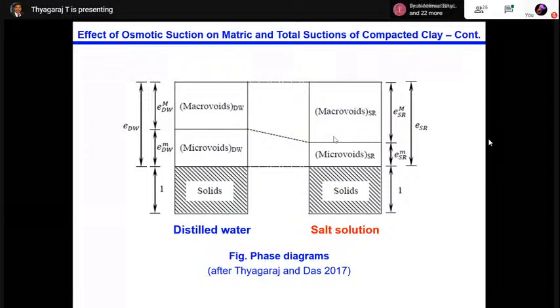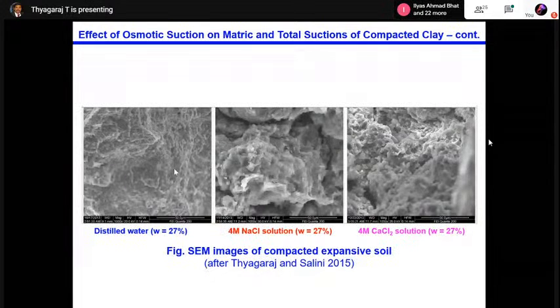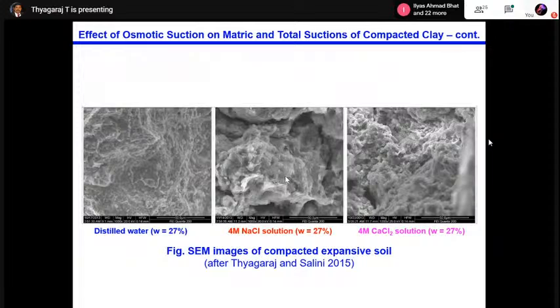Since this happened, it can also be seen through the SEM. You can see clearly that distilled water has a uniform fabric, whereas with the salt solutions it is aggregated. You can see that the macropore sizes are increasing because of the aggregation.